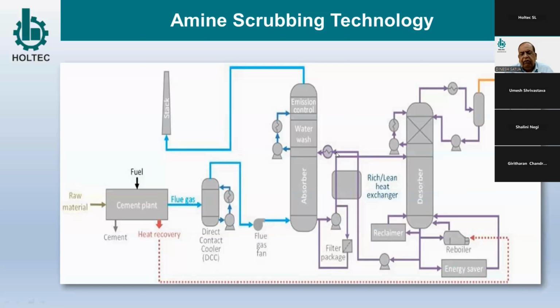We will just give you a brief about what the process exactly is, just an idea. In the cement plant, we get flue gases, which will be pre-treated. We know CO2 is normally 18 to 22%, but typically it also has NOx, SOx, dust and water vapors. All these can create problems with the use of MEA, so they have to be removed first. The temperature is reduced to 30 to 40 degrees, and the gases are scrubbed. SOx, NOx, even dust is filtered from there.